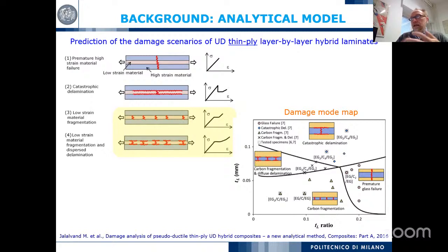There have been studies and analytical models that can be used to create this damage mode map that can help us to distinguish which damage mode is going to appear in the material according to the ratio between the two different materials we use in the laminate. And so this is very interesting because we know that if we can create a sort of fragmentation in the low strain material, or we can create fragmentation with initial delamination at the interface between low strain and high strain material, this can result in a pseudo-ductility that we can observe in the stress strain curve.